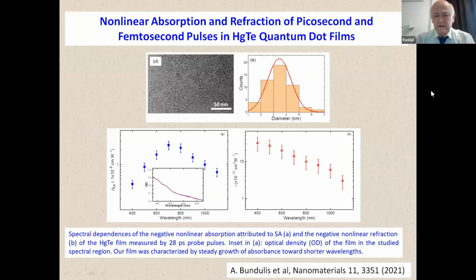Another material is quantum dot films. We analyzed mercury telluride quantum dot films as well as other quantum dots and some nanoparticle films to create samples which could be used for practical applications like optical limiting and mode lockers for lasers. The first sample is mercury telluride quantum dots with sizes of a few nanometers. We used 3 to 4 nanometer quantum dots,